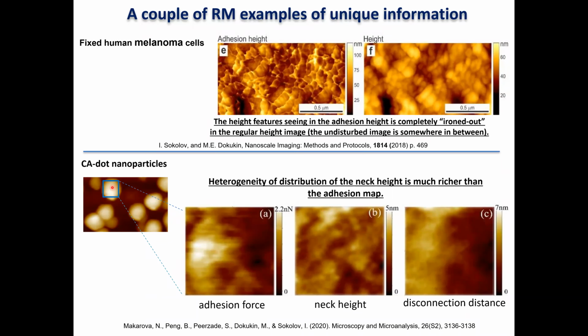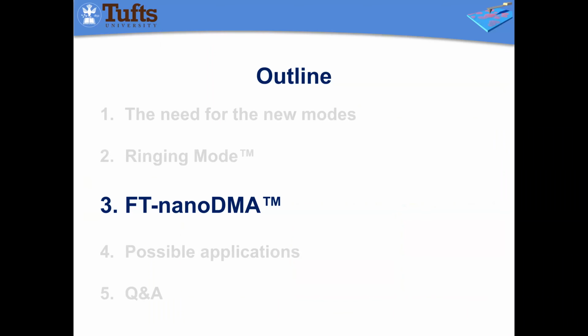Nanoparticles. If you really go to individual nanoparticles, you can look at, for example, material of nanoparticles, neck height, disconnection distance, coating of nanoparticles, coating with some functional molecules, for example, or just whatever molecules grafted onto the surface of these particles. And you can compare adhesion, neck height, and disconnection distance, and you can see there are some correlation, but not necessarily. So all these 3 maps give you different physical information.